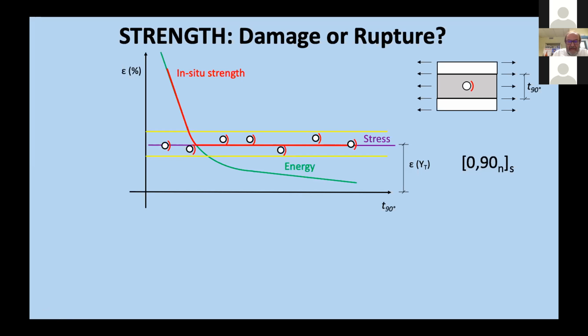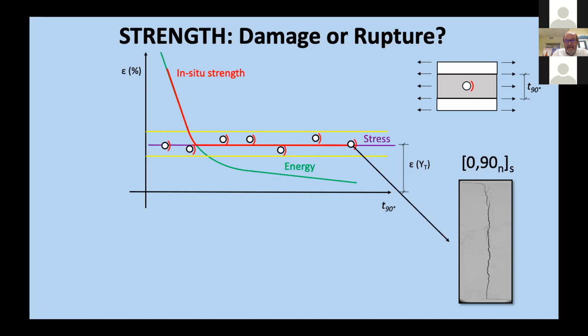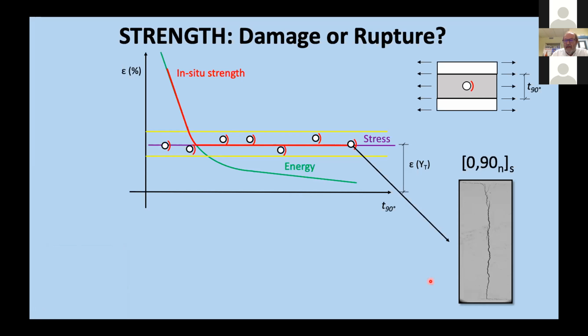However, when performing tests, the first thing you see of damage is that indicated here for a very thick 90-degree lamina. So suddenly, with no previous indication, you will have a complete breakage of the lamina associated with delamination.